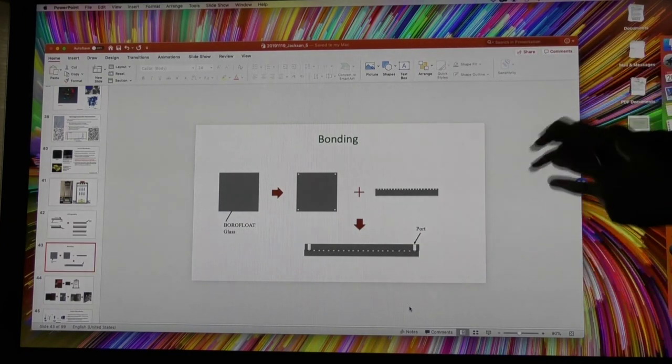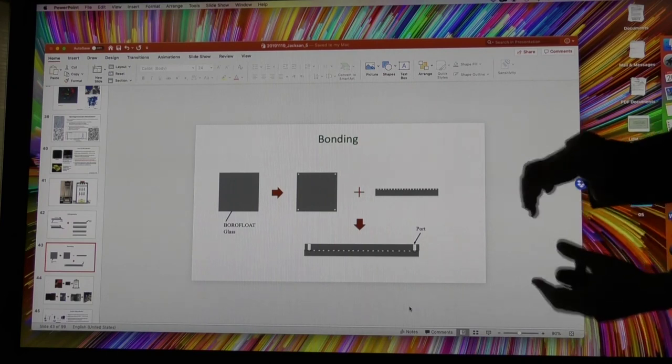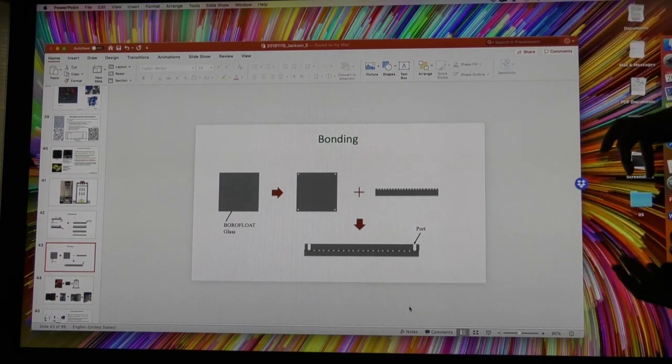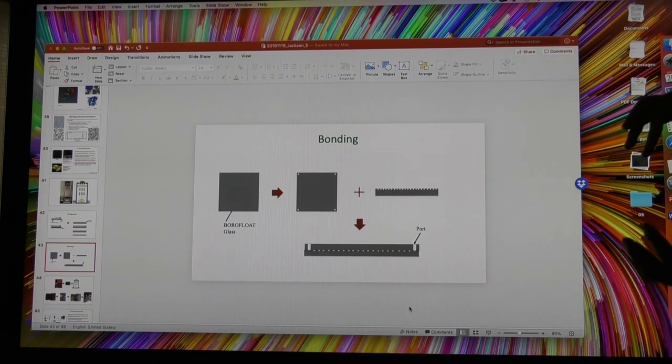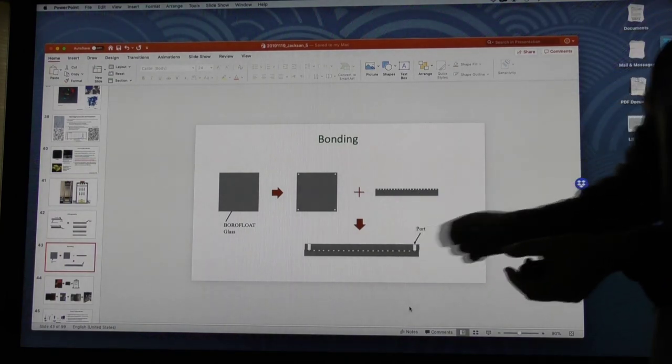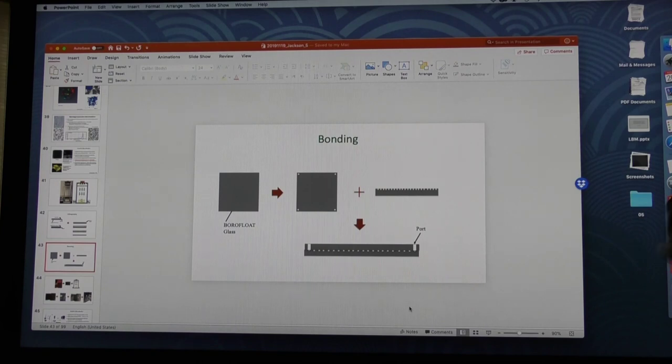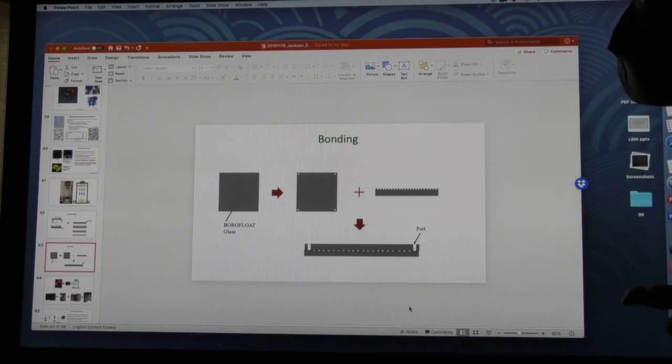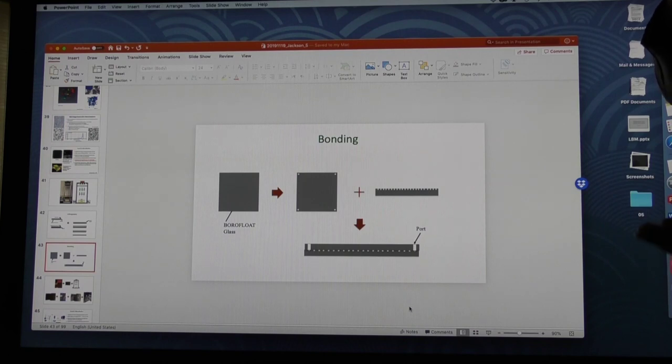And then there is a system we've designed over the past couple of years. We've kind of fine-tuned this. There is an oven. We have, it's not steel, it's a, they use it for spaceships. There's a particular alloy that's really resistant to temperature, and we have plates made out of it. We have ceramic inside. And we put the sandwiched glass substrates between the ceramics that are sandwiched by this special alloy. It's called Hastelloy X. And then this whole sandwich setup goes inside the furnace, and the temperature goes up following a particular protocol.